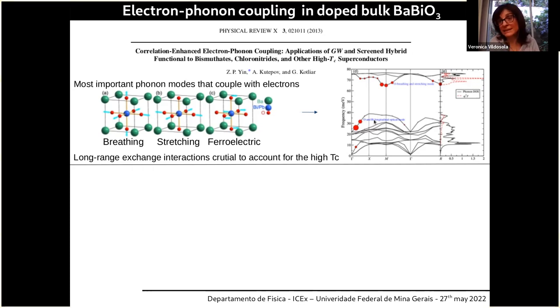And the point was that the gap was not well reproduced. The Peierls distortion was not very properly described with GGA. So you need more precise techniques. And they demonstrate that if you use either a GW or a hybrid functional, you can obtain an electron-phonon coupling that is 3 times the one that you obtain with GGA. And with this correction, they could explain a high TC of 30, 32 kelvins in this material.